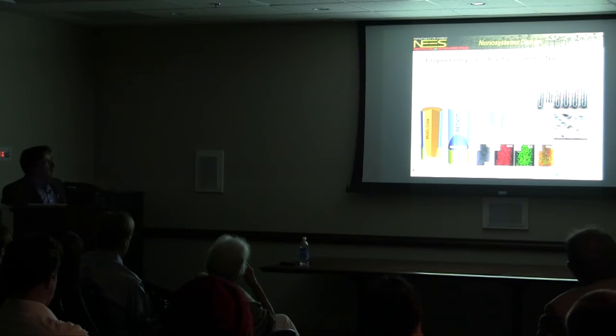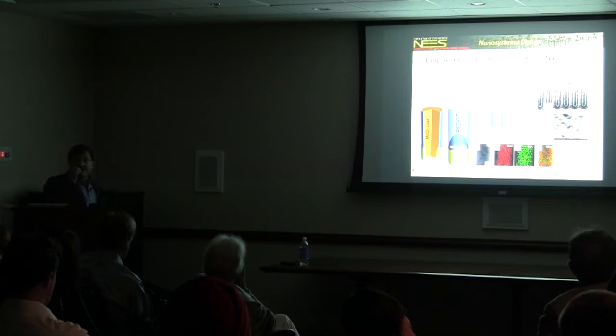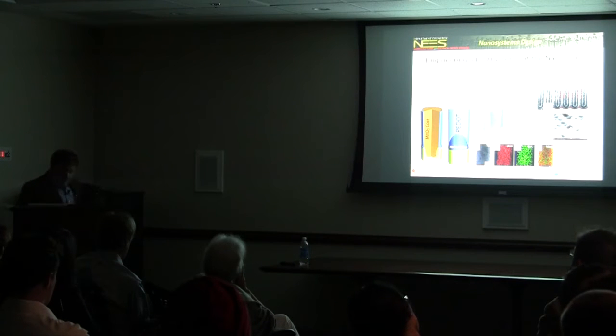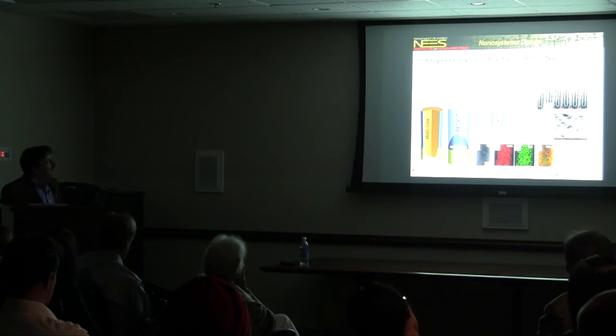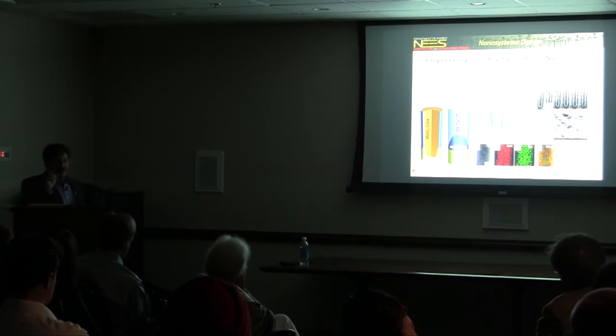These were our metal insulator metal structures. And they start with that scalloped surface, which unfortunately has sharp peaks. And so those peaks end up at the top here. And when you build a structure that goes over that peak, you have a high field concentration, which leads to low field breakdown and other kinds of characteristics. So we really have to engineer the shape of these things below the nanoscale of the structures that we make in the beginning.